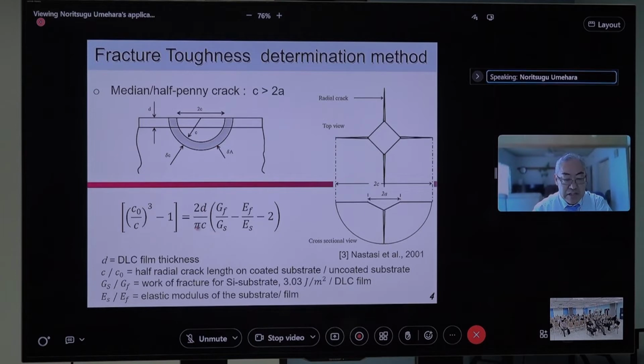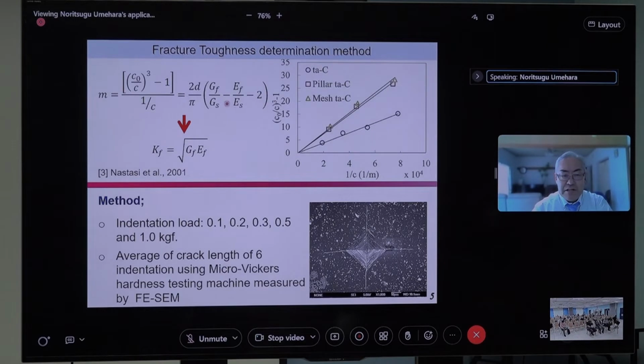And so if we know the C value and the C0 value, where C is the crack length with DLC and C0 is the crack length without the DLC, and we know this equation, we can get the GF value. GF is the work of fracture of the DLC material. That is our target. By such a way, if 1 over C is increasing, this value is also increasing.